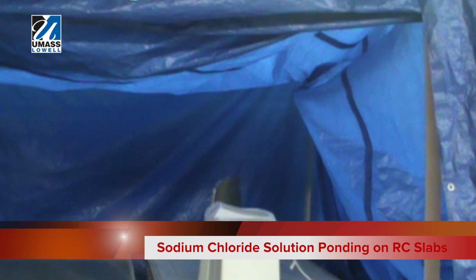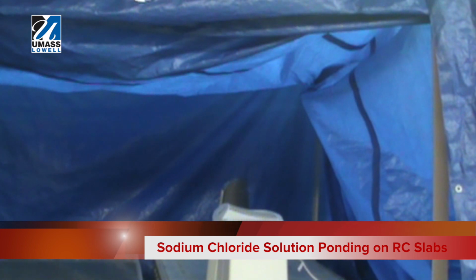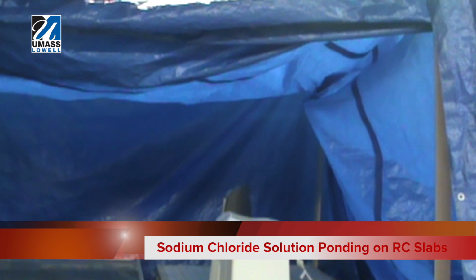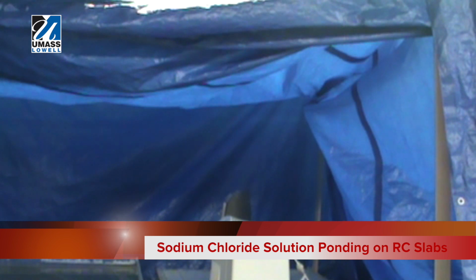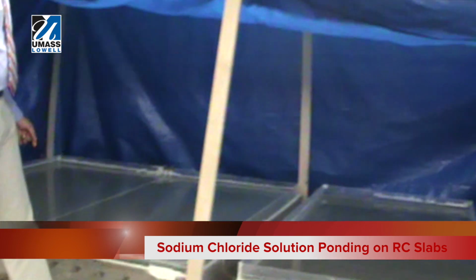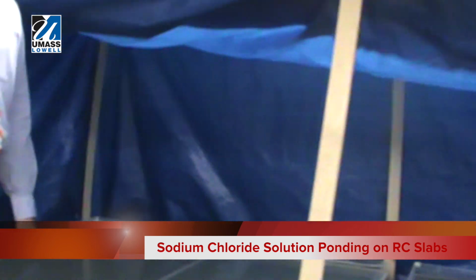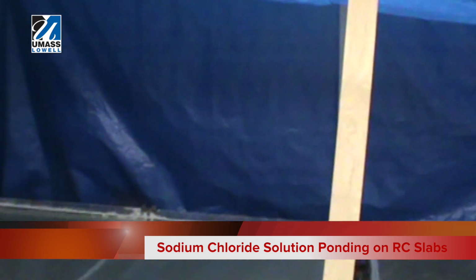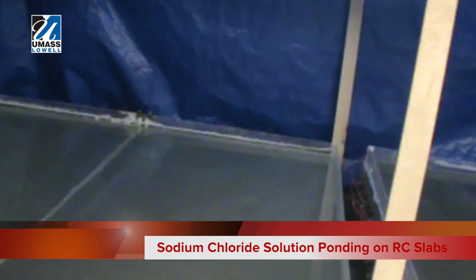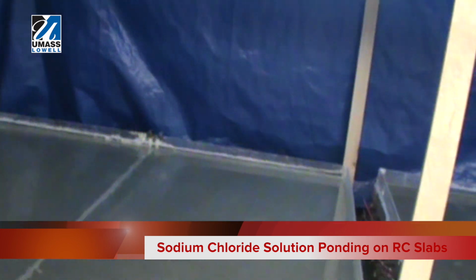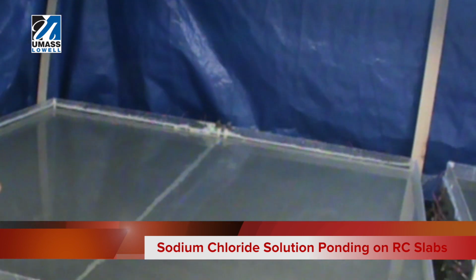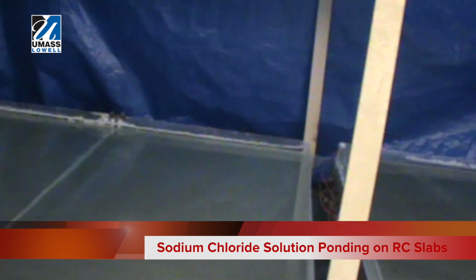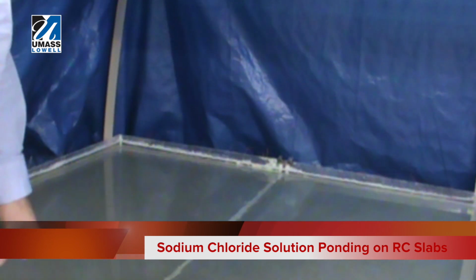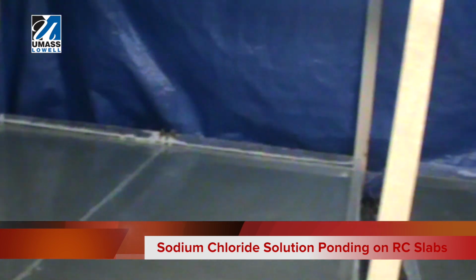Slab number 3 and slab number 4 are exactly the same, except that slab number 4 is the control slab, and slab number 3 is subjected to ponding. The ponding solution that we have been using is 15% sodium chloride solution by concentration. The ponding begins on Friday afternoon and ends next Tuesday after that. So there is a 4-day wet cycle and a 3-day dry cycle.